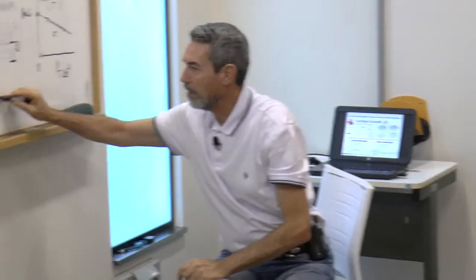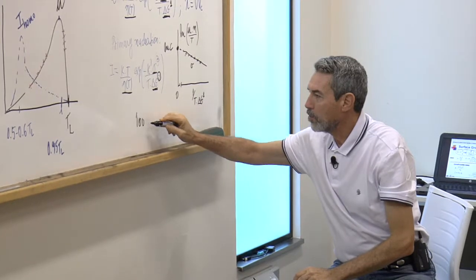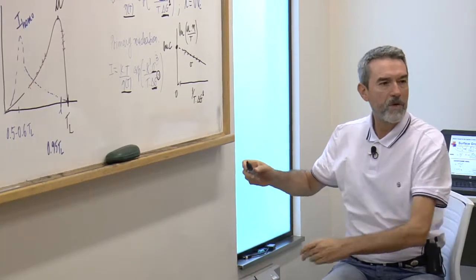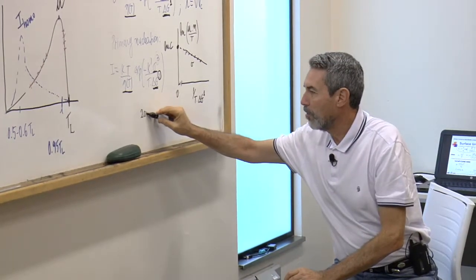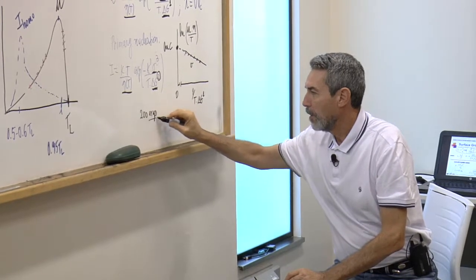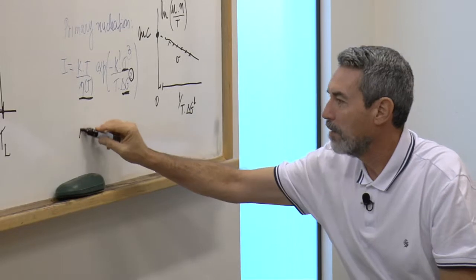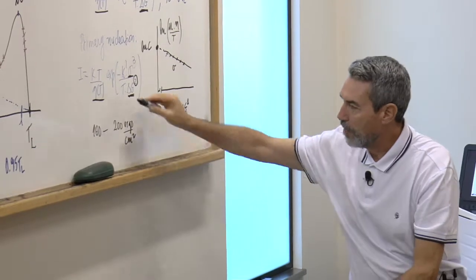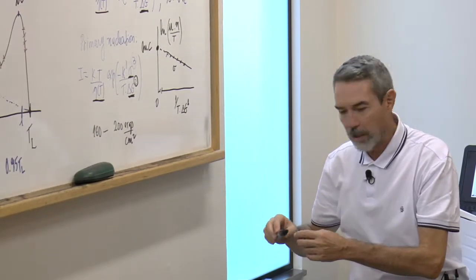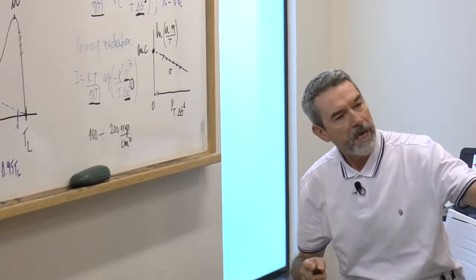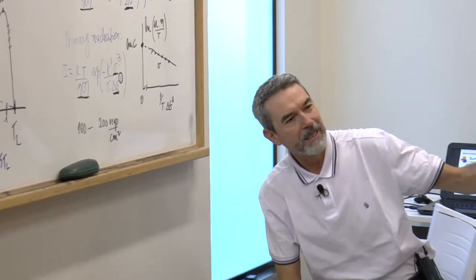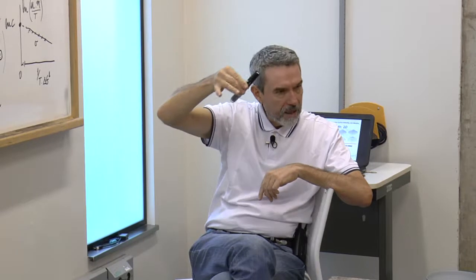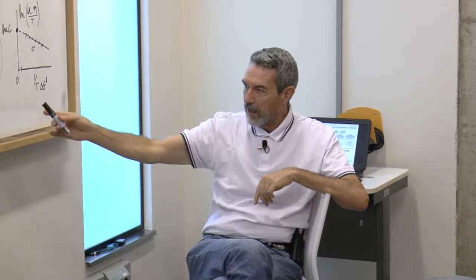In ergs, normal values are 200 ergs per square centimeter, 100 ergs per square centimeter, something in this range, the same range that you got from your nucleation experiments. You got a value of sigma from your nucleation fitting exercise, somewhere in this range.